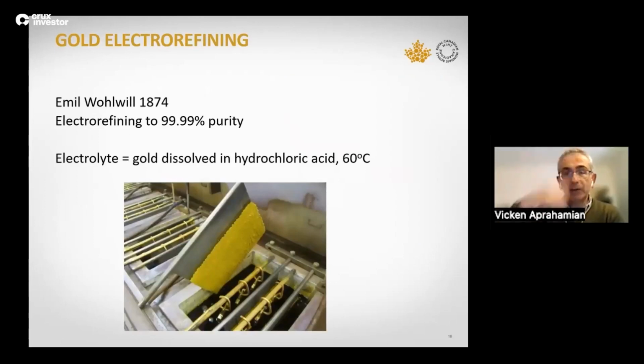And the final stage of refining is, again, a very mature process invented in the 1870s in Germany. Here it's essentially placing the anodes in a gold chloride electrolyte, passing a current and plating out the impure gold into a purified form on titanium starter sheets. This is all done obviously in a hydrochloric acid system at 60 Celsius.